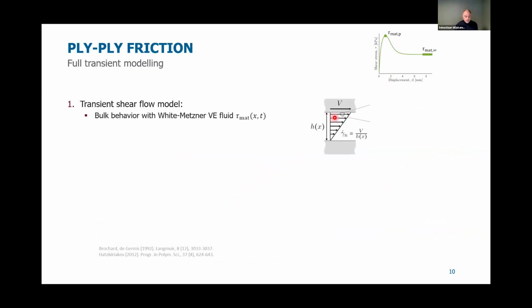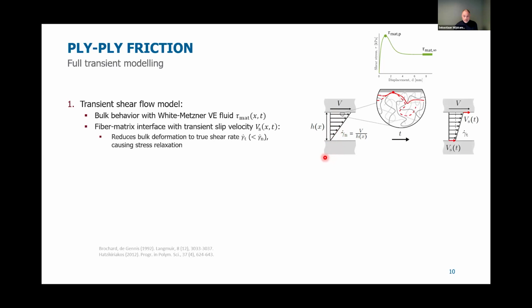Our researcher chose to describe the bulk behavior of the polymer with a White-Metzner viscoelastic fluid and look at slip at the polymer matrix fiber interface. And we hypothesized that this is really the mechanism that will lead to an increasing slip velocity, with which you can actually describe the decrease of the shear stress, starting from the peak stress.